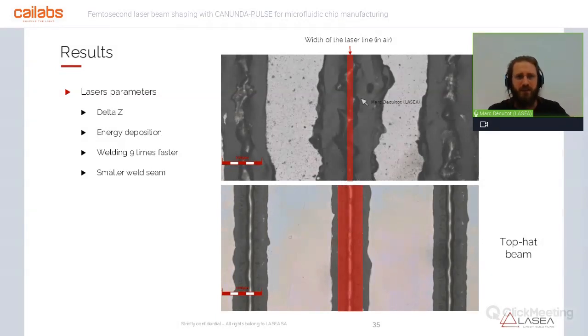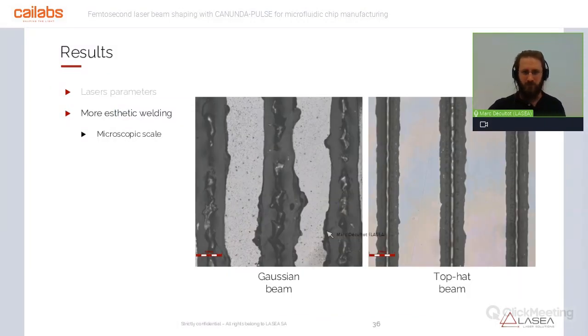Another interesting thing is the difference of size between the laser line, which depends directly on the diameter of the spot size, and the welding seam. We have a huge difference between the width of the welding seam and the width of the laser line in the case of the Gaussian beam. In the case of the top hat beam, the widths seem equivalent. It's faster and smaller, but we also observe a more aesthetic welding at microscopic scale. As you can observe here, the edges of our welding seam are clearly more irregular in the case of the Gaussian beam than in the case of the top hat beam.